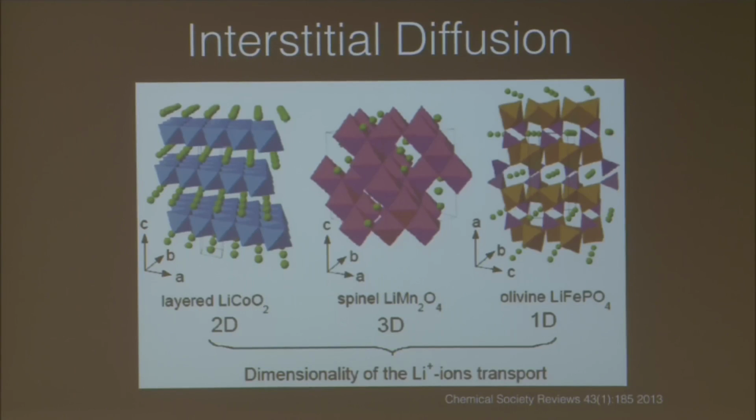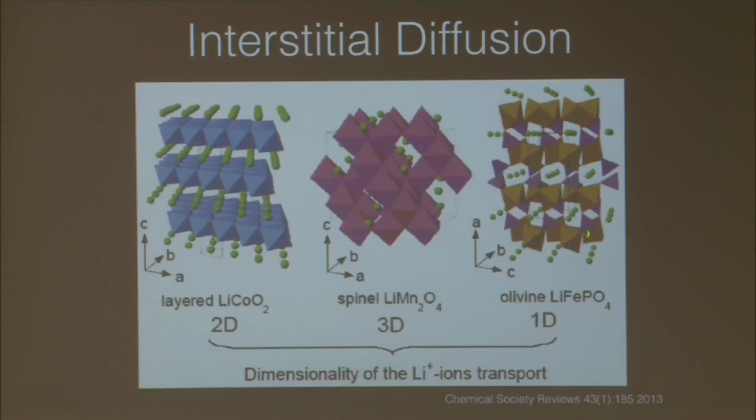What is the activation energy for a lithium atom in a given material? And does it take a 1D path? It turns out these can be extremely efficient. Look at those. They're practically holes. They're lines in the lithium iron phosphate. That's a really nice cathode material because you've got these channels, these high conduction channels, these highways, right?